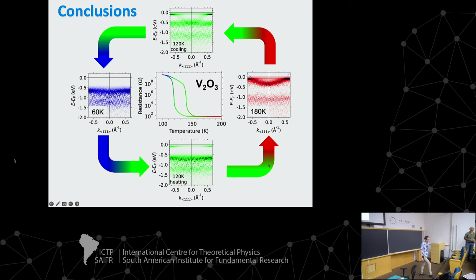So, but here, keeping the dimensionality of the system, it's 3D. It's 3D, yes. But you're lowering the temperature. So could I understand, does this very simple-minded picture still hold, that by lowering the temperature, you're effectively decreasing the ways along which electrons can avoid scattering off each other, and that's effectively decreasing the strength of electron-electron interactions? Or to be more direct, do you have a way to measure how electron-electron interaction strength varies with temperature, or estimated? We don't have yet.